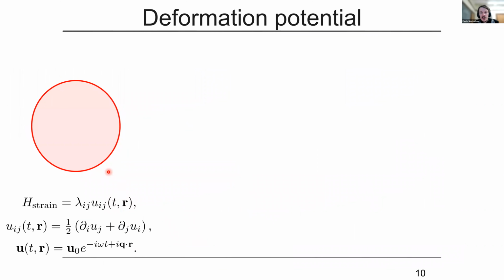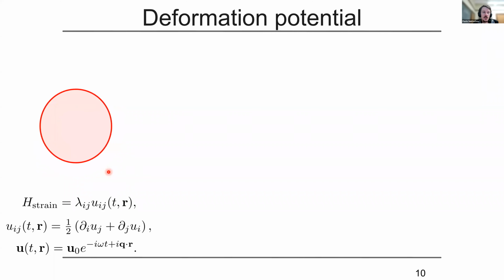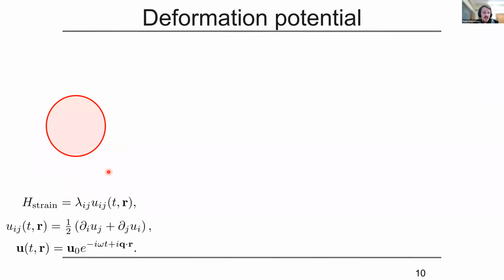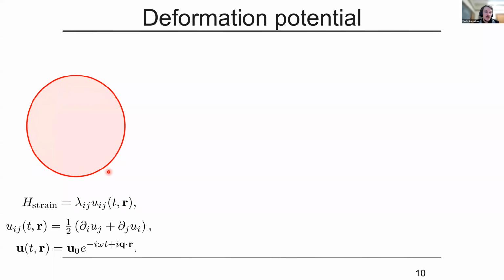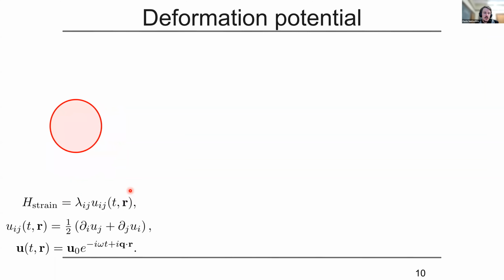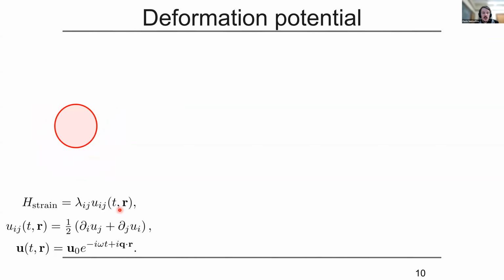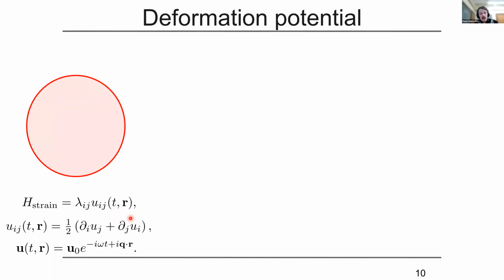If we deform a lattice, of course, electrons will follow, and if there are any excitations on top of the Fermi surface, these excitations eventually will lead to the dissipation of our sound energy. So mathematically, strains can couple to the electron dynamics with the so-called deformation potential, which looks as follows. The following term is in the Hamiltonian, where u_ij is just a symmetrized strain tensor.